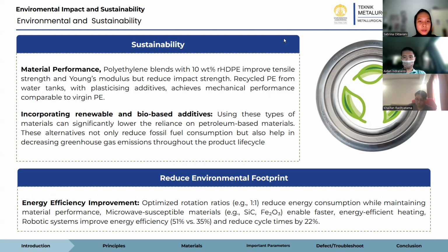For materials performance, polyethylene blended with 10 wt% rHDPE improves the tensile strength and Young's modulus, but reduces impact strength. Recycled PE from water tanks, with plasticising additives, achieves mechanical performance comparable to virgin PE. For renewable and bio-based materials, we can use these types of material that can significantly lower the reliance on petroleum-based materials, and alternatives not only reduce fuel consumption but also help decrease greenhouse gas emission throughout the production life cycle. And for energy efficiency improvement, we can optimize rotation ratio, reducing energy consumption while maintaining material performance.